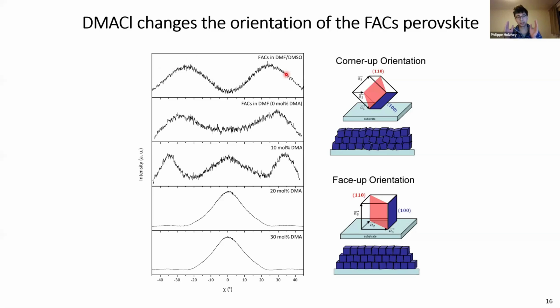And then the moment we add the DMA, so it's 10%, and then with 20%, we see the alignment of the grains. And here's sort of like a schematic, which means that the unit cell in its orientation becomes oriented with the substrate below. And that means that you have a face-up orientation. So the 110 faces you the moment you look at the substrate. So you can imagine that the grains are more uniformly distributed.